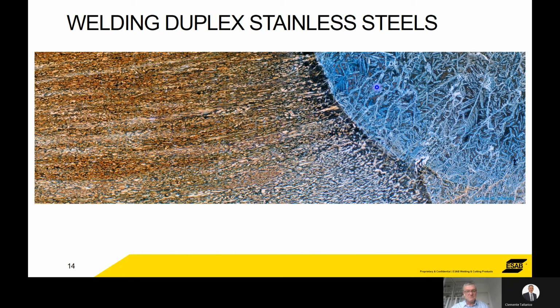There are four things in particular to take note of. The first one being the joint preparation. With stainless steels, the more highly alloyed they are, the fluidity of the weld pool is not so good. So the design of the joint needs to be such that the root gap, for instance, is wider. This is to allow the sticky weld pool to flow into the gap. If it's not taken into consideration, then there's a possibility of getting things like lack of fusion. You're not going to get the weld pool to flow into the joint.